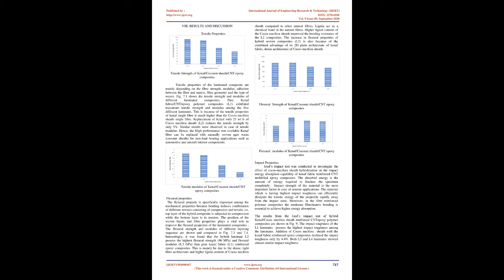Tensile test setup. Flexural testing. The flexural test was carried out according to ASTM D790 with a specimen size of 120 mm x 20 mm x 3 mm through 3-point bending test using an Instron 5566 universal testing machine, UTM. The standard span to depth ratio of 16:1 was considered. The magnitude of load and the rate of loading were 10 kN and 2 mm/min. 5 identical samples were tested for each layering sequence and the average results were reported.